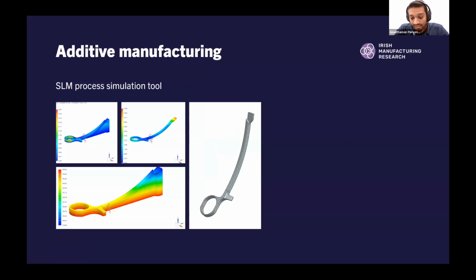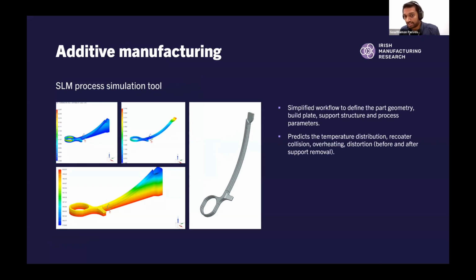And also, I mentioned additive manufacturing a lot, and we need to use the right set of processing conditions to print the part right the first time. This is often really difficult, and simulations can play a role in helping us there as well. So the Siemens additive manufacturing tool can help us define the part geometry on the build plate with support structure, and then we can run the simulation to predict the temperature distribution. We can know whether there'll be any recoater collision, whether there'll be any overheating in the layers, and whether the part will distort before or after the support removal.